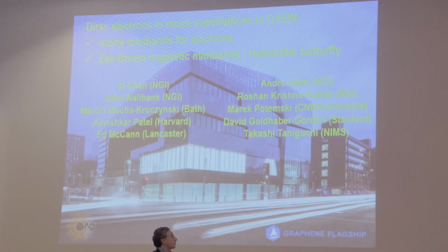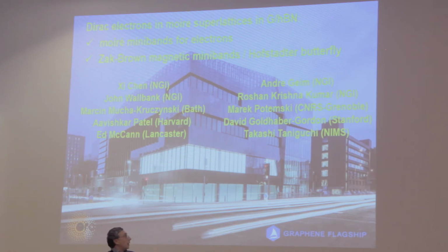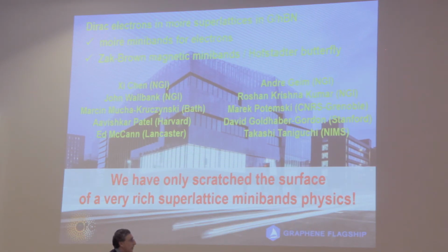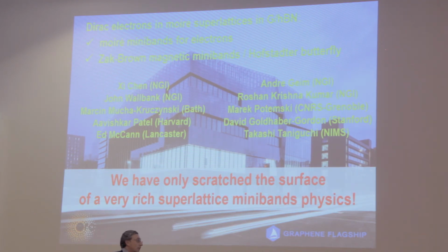To conclude, I have told you about what happens with Dirac electrons in Moiré superlattices in graphene heterostructures with boron nitride. At low magnetic fields, we have very strong evidence and very clear miniband behavior of electrons in the Moiré superlattice. At strong magnetic field, we also start seeing the magnetic minibands predicted by Zak and Brown. And I would like to say that I think we have only scratched the surface of the very rich superlattice physics in these heterostructures, and most probably the most interesting part of this physics is related to the interaction between the electrons when they are in these minibands.